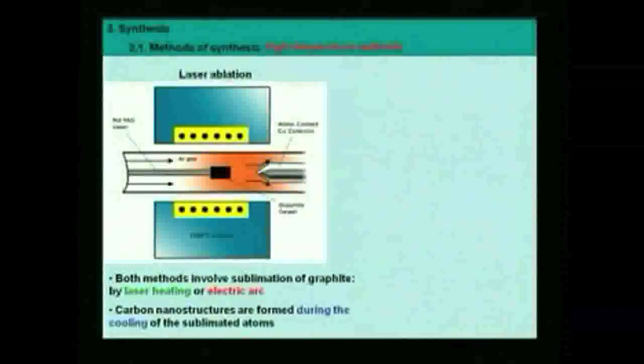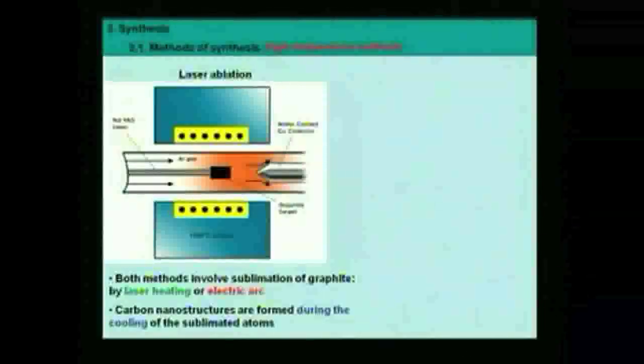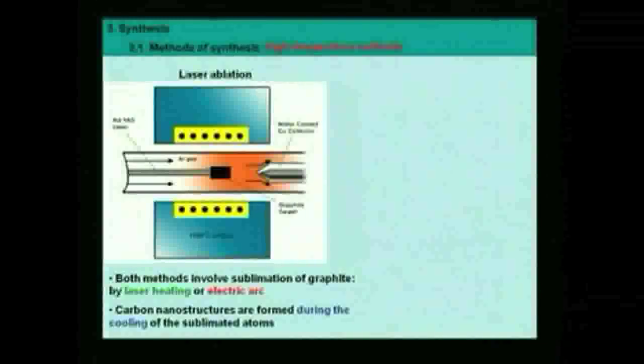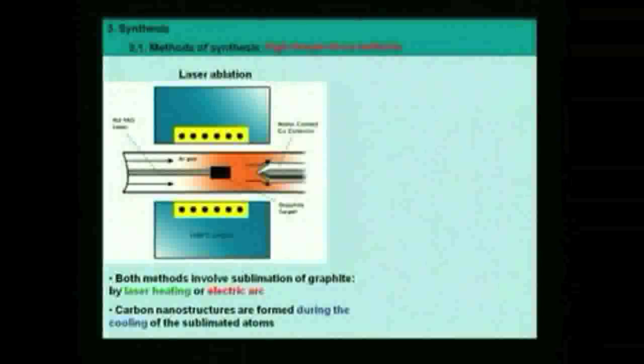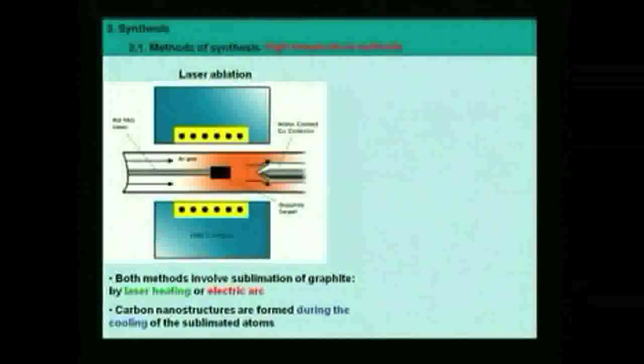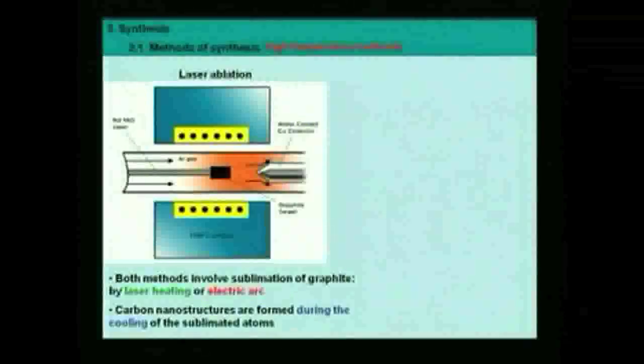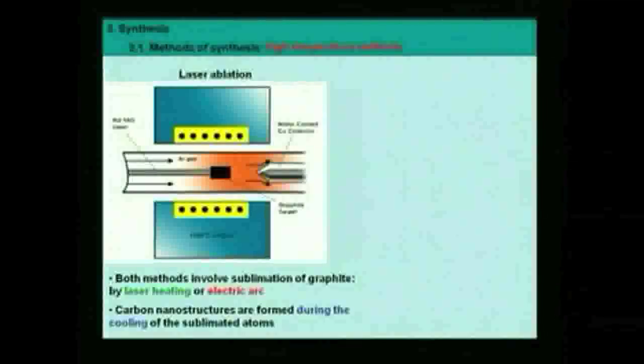Okay, now we are going to describe these techniques, starting by the high temperature ones, and then we will go to the medium temperature one. First technique is laser ablation. As I already said, we are going to use a laser to heat a solid carbon source, which is a piece of graphite, heat so much that carbon atoms here at the interface will sublimate, become vapor. Then we will form like a cloud of carbon atoms, and this cloud will move because of the flow. Here we got an argon flow in this direction, and during this travel, it will cool down. The carbon atoms will cool down, and new solid carbon structures will form.